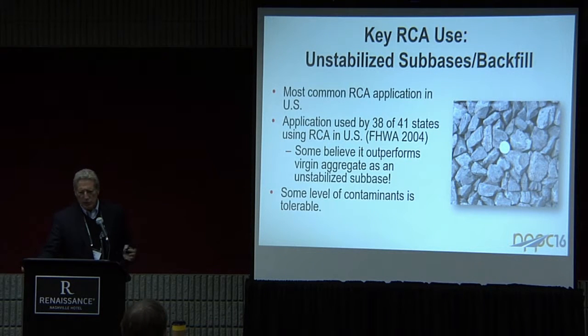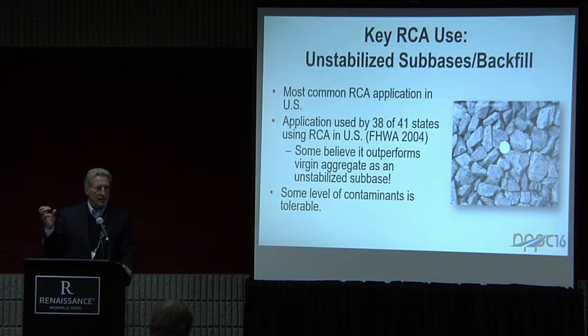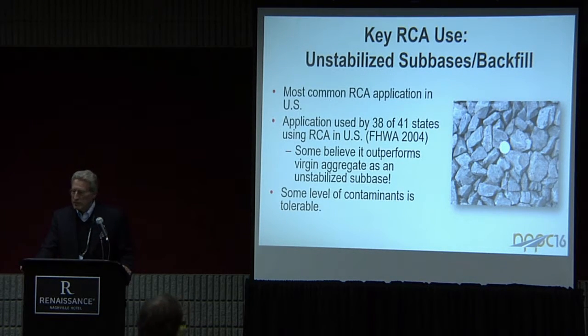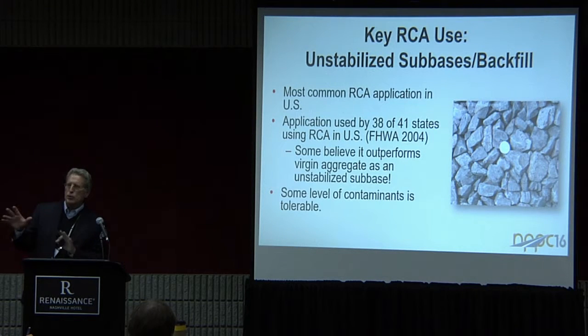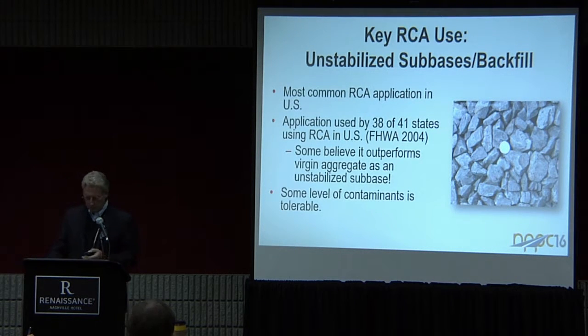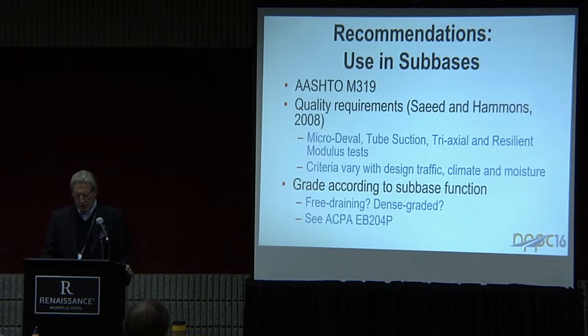So the two key uses we have: unstabilized subbases and backfill materials. Again, the most common application in the U.S. At least 39, 40 states that I know of are using it currently. And as I said, a lot of folks think that it is better than using natural aggregate in many cases because of that secondary cementitious action. And it's fairly easily implemented because some degree of contaminants, considering joint sealant materials and asphalt, perhaps not contaminants per se, but not pure concrete, let's say, is tolerable. And fortunately, it's been pretty well implemented already.